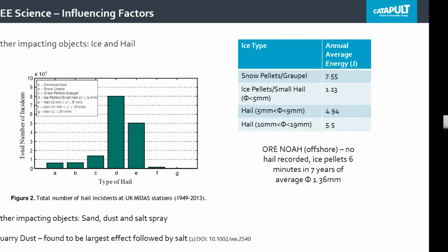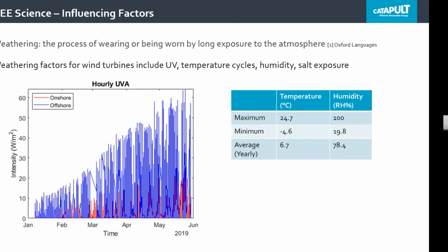Sand generally is dealt with by testing to the ASTM G76 sand erosion test method. But there was a study conducted in Ireland with Suzlon, which showed that onshore, if a wind farm is located near a quarry, then that had the highest significant effect of erosion on turbines, followed by salt on nearshore turbines.